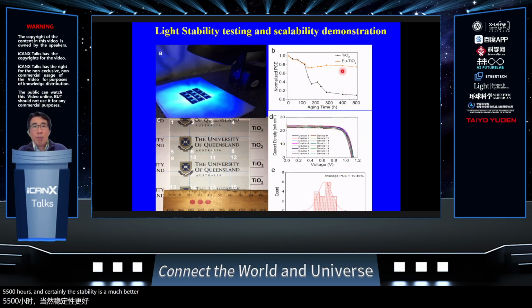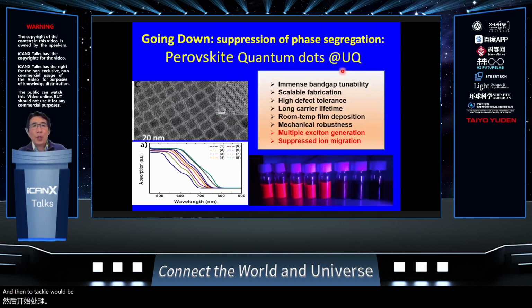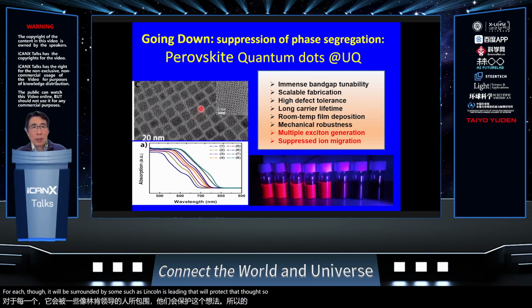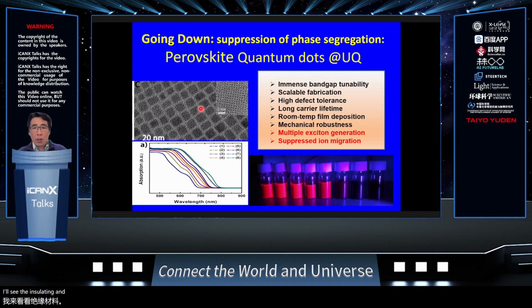And then to tackle the intrinsic ion migration within the bulk film, we try going down. That means we try to decrease the particle size to as small as possible, which leads to perovskite quantum dots. In quantum dots, each dot is surrounded by some surface ligand. This ligand protects the dot, but the ligand also has the problem of being insulating and blocking the charge transfer. How to reach a balance is a tricky thing.